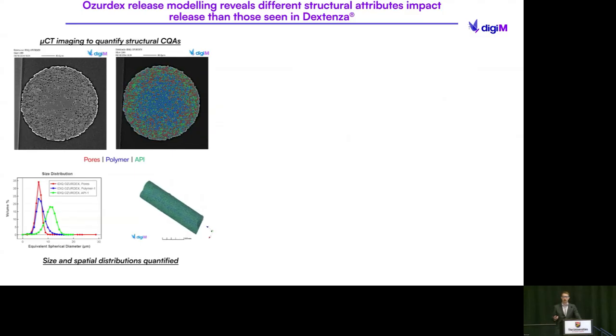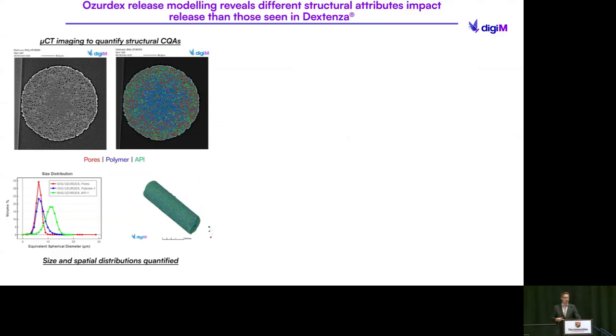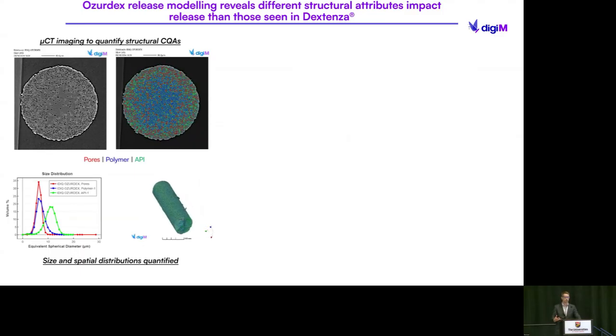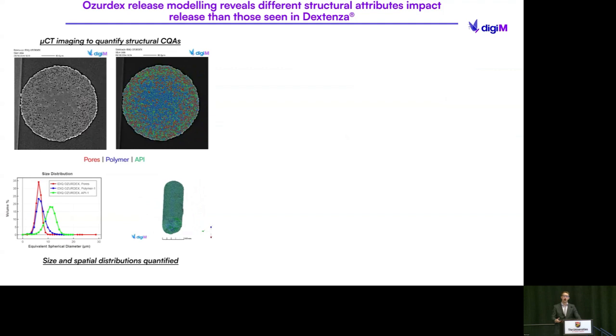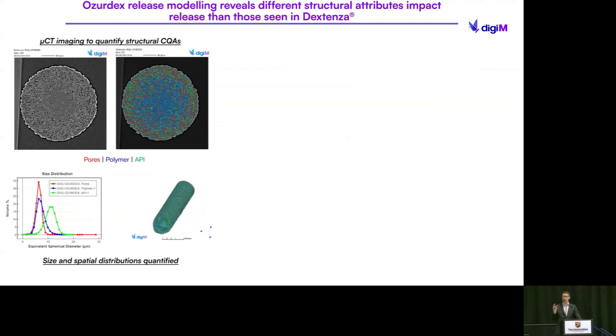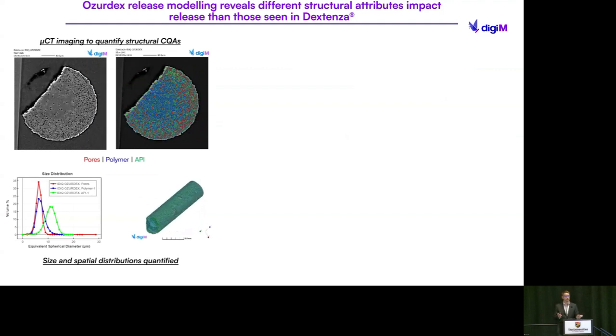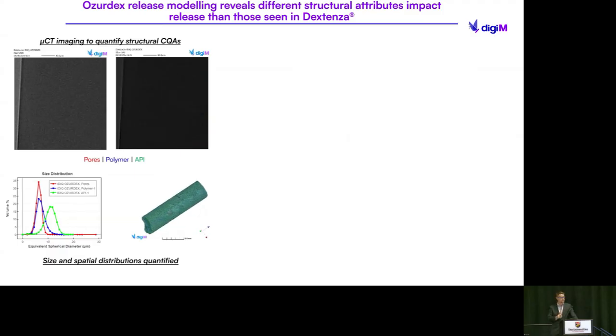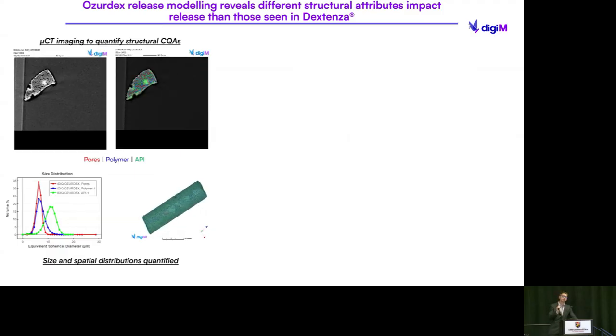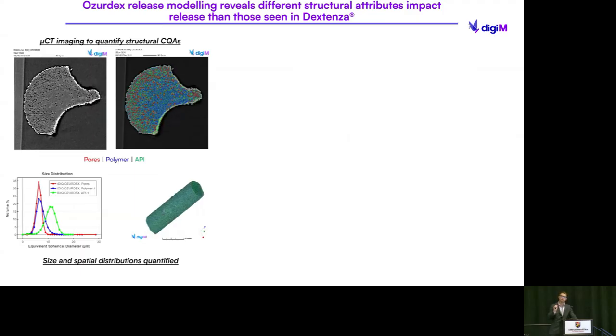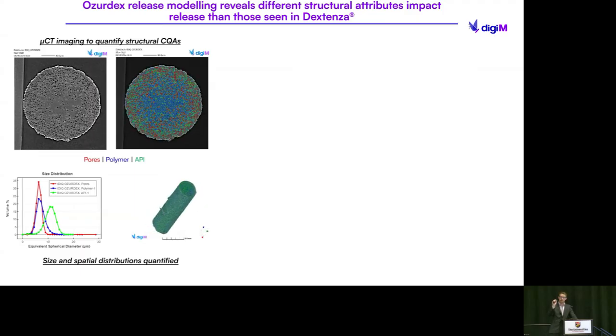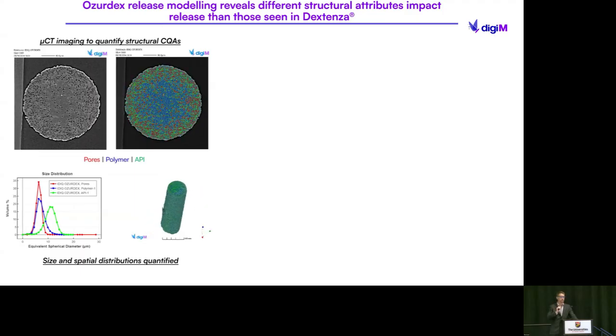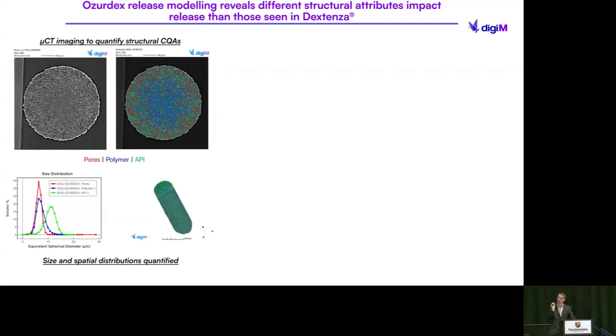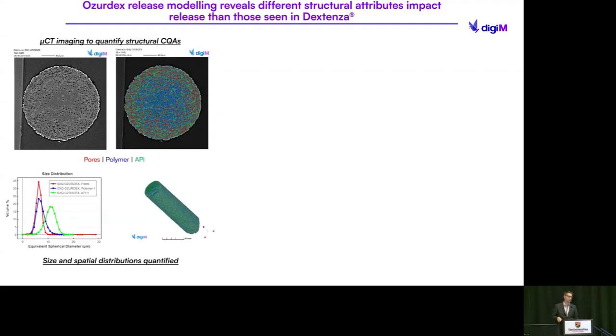The average size of the API that goes into Ozurdex is around 2 microns in diameter, which is a really difficult size range to hit with micro CT, especially to quantify it exactly. Not because it's hard to spot the API, but at the amount of drug loading we're looking at, the polymer gaps between the particles become a challenge to actually spot. They're so small that they're below the pixel limit.